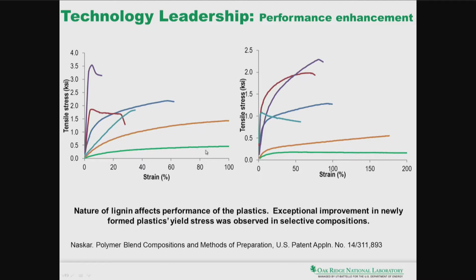So we tailored the different formulations here. As you can see, we added some other additive, and then we are seeing the tensile deformation curve is changing significantly from rubbery to, in fact, some plastic deformation, yield stress, you can see. And this is a very encouraging result. We improved the mechanical properties almost 3.5 times and showing some yield stress. And based on that, we learned a lot, and we are further working on it.